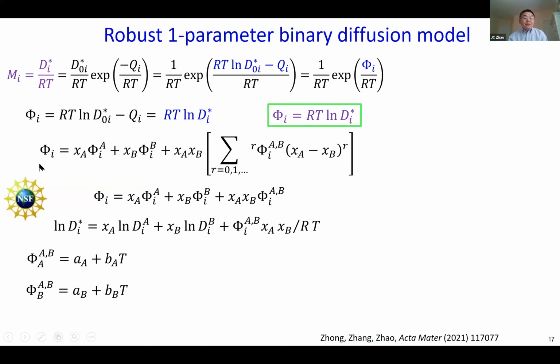So if you have a binary diffusion system, AB, that's how it writes out. If R equals 0, then you get a single parameter. Usually people use A plus BT for each element, so you get 4 parameters, 4 constants to fit, right?